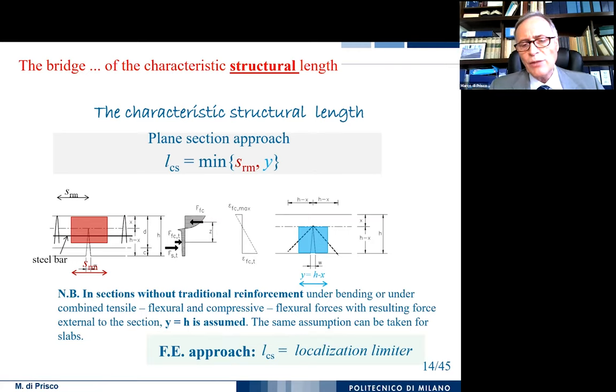Of course, this is not valid for the finite element approach, because in that case, we don't use the plane section kinematic model. We use another type of model. And so in the next lecture, you will go deeply into this problem, because changing the type of finite element, we also have to change the characteristic structural length, which essentially is a way to spread the crack opening in a different zone corresponding to the crack band.